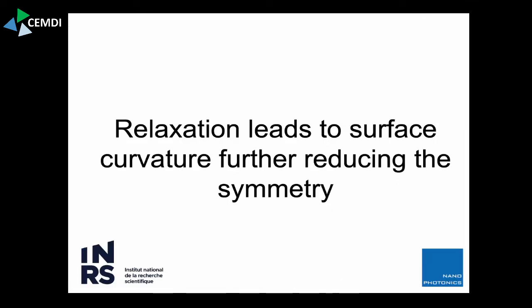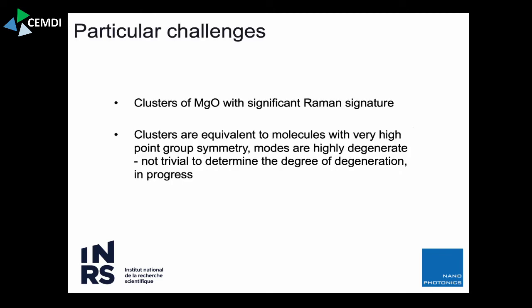And the next thing, this was done on an unrelaxed structure. If we let it relax, the surfaces actually kind of bend outwards. They have a slightly conical shape. I don't know if that's an artifact from the simulation, if that's real. I know that nature then would at some point try to change the Miller indices of surfaces if the center has too much curvature. But if there should be a real, ever so small bending of surfaces, that would further reduce the symmetry, and that should give rise to an even larger number of Raman active modes. So that could be an interesting thing to follow up on, also in terms of simulation, if the bending of the surfaces is real. But that means dealing with these crystals as if they were macromolecules, just with a high symmetry. And so they have these signatures, and yeah, we treat them kind of like molecules.